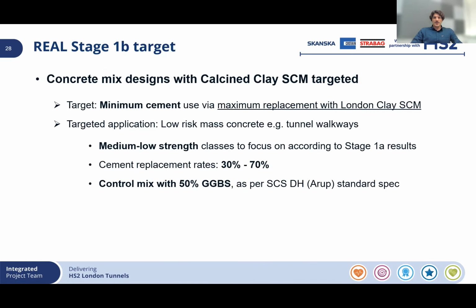So the mixes that we are targeting were aiming to minimize cement use, to use the absolute minimum cement content. For example, if we could use 280 or 240 kilograms per cubic meter, we would be happy with it, and target the low strength applications, which means approximately 20 to 25 megapascals at 28 days, with cement replacement rates with the calcined London clay varying from 30 to 70%. And we would compare the results to our standard 50% GGBS mix, which is the mix that's been used as a control mix. It's a minimum standard specified mix in HS2, at least for the contract that we are involved.